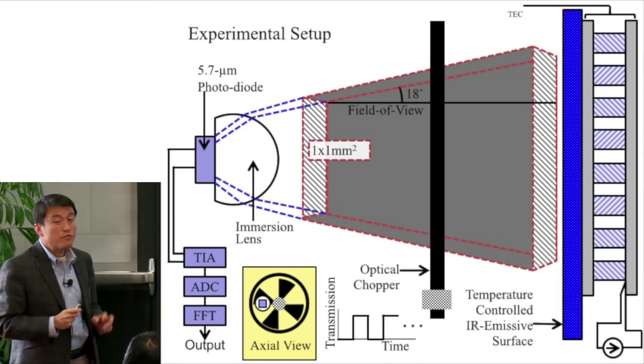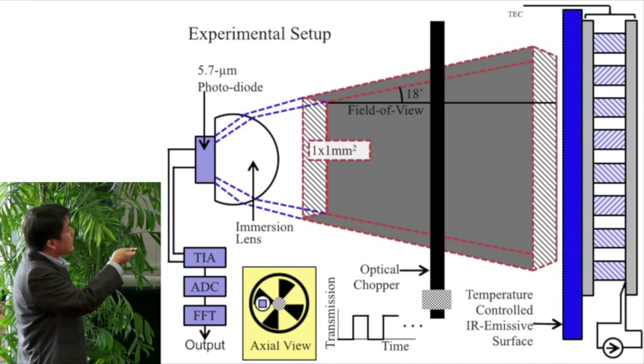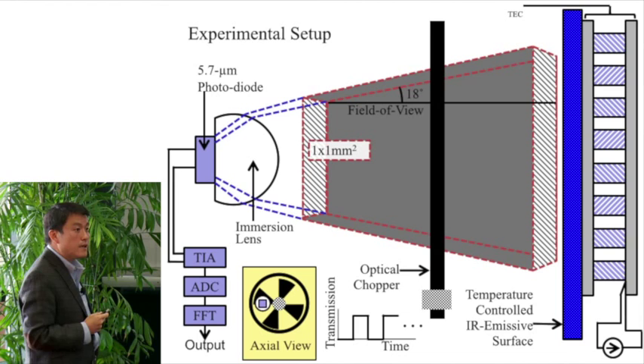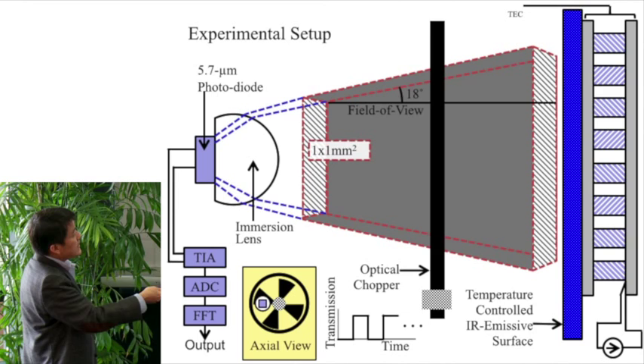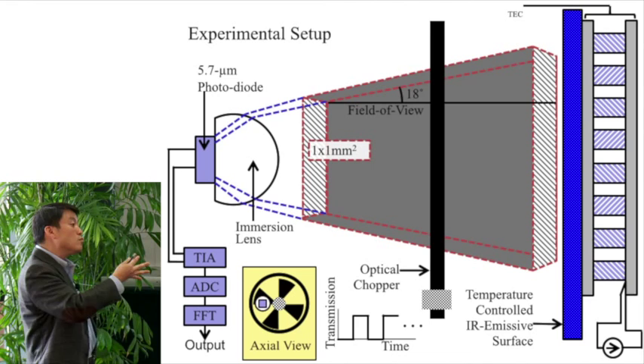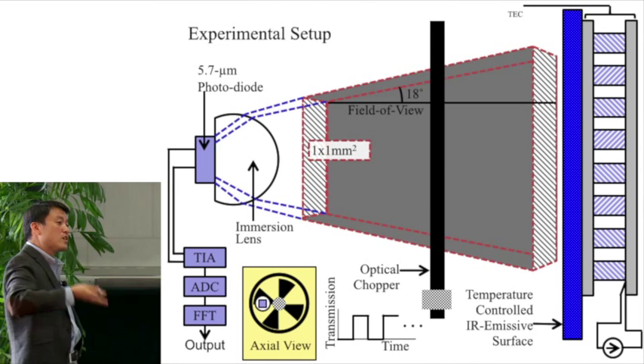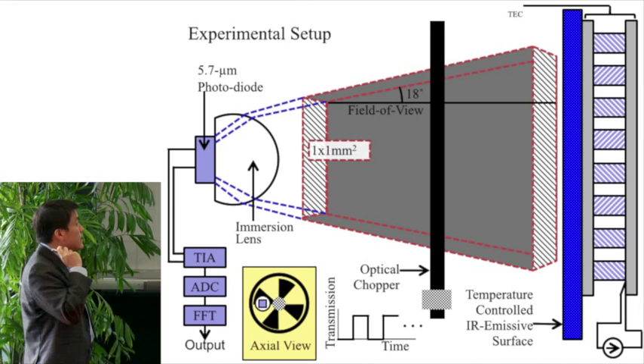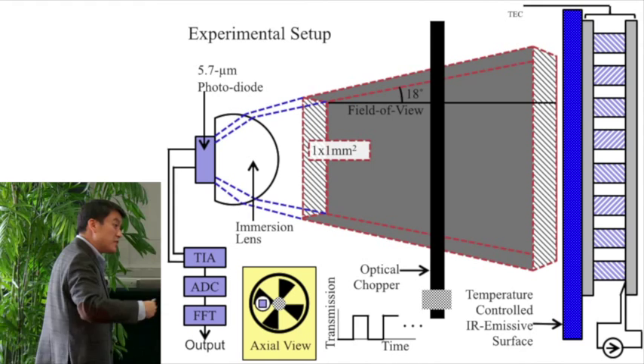So what we did is we used a long wavelength photodiode. These are mercury cadmium telluride photodiodes. And then we basically have that diode facing a temperature-controlled IR emissive surface. And to do a reliable measurement, we put in an optical chopper. This essentially looks like a fan. And as it rotates, sometimes the diode will see the emissive surface, sometimes it will not, as the fan rotates.